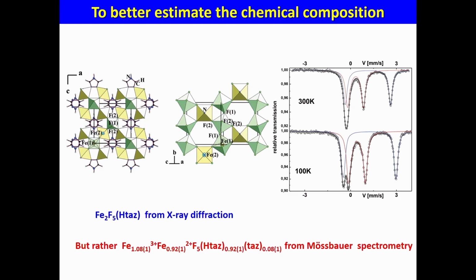What we can do is to do a spectrum at low temperature. Low temperature means 100, because below it was magnetically ordered. But the proportions were the same. That means the F factor was the same for the 2 positions.